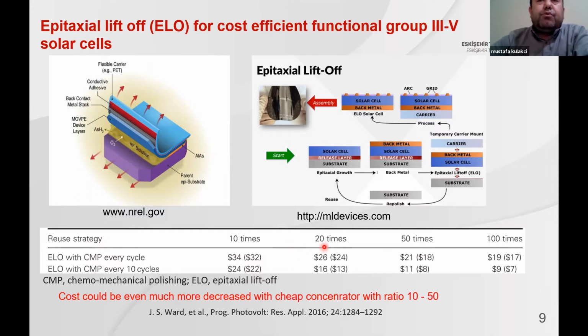In 10 times use, 20 times use, 50 times use, and 100 times use, with chemical mechanical polishing, with mechanical polishing or without mechanical polishing, you see the substrate cost. Actually this is for a 6-inch substrate, and they assumed at the beginning the substrate price is $150, but it is not realistic. Of course, maybe in huge production it can be realistic in future, but today it is not realistic. Also, Alta Devices confirmed 10 times use of gallium arsenide substrate without any change in sequential device processing. There's no change in efficiency in the devices.